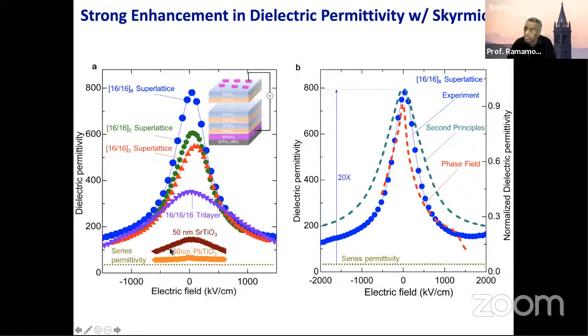Now, if you measure pure lead titanate, you should get a permittivity of the order of about 70. Okay. 50 to 70 is a good number. Similarly, if you measure pure strontium titanate, you should get a permittivity of the order of maybe 150 at room temperature. Instead, we were getting a value of about 800 in a superlattice where you had series combinations of dielectrics. And we said, oh, that's very fascinating.